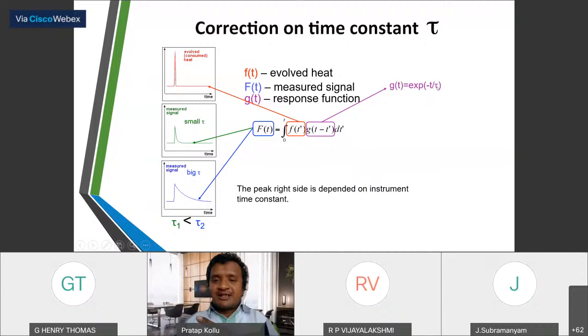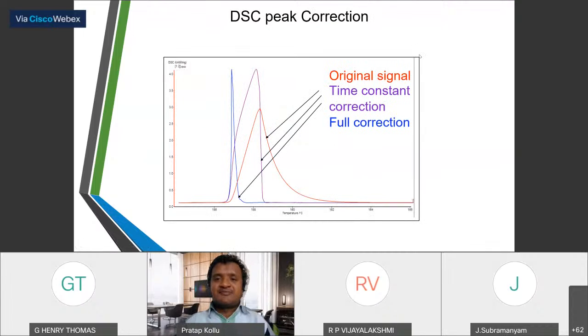So you look at the graph in the next slide. So look at it here. So the original signal is the red one. After measuring a DSC, the original signal is the red one. And this one, the lavender color one, is corrected for time constant. And this is corrected for thermal contact also, the blue one. So now look at the graph. So the melting point is somewhere around 157, but we got it as 159. So corrections are necessary for DSC.